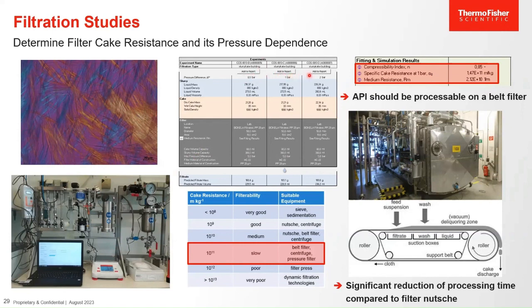We do experiments at 3 different pressures, and in this particular case, we found a filter cake resistance of 1.5 × 10^11 meters per kilogram. And if we look at this table here as a guide, this tells us that this is a slow filtering material, and the best equipment for this type of material is a belt filter or a centrifuge or a pressure filter. Pressure filters are not very common in the pharmaceutical industry. We have centrifuges and a belt filter.